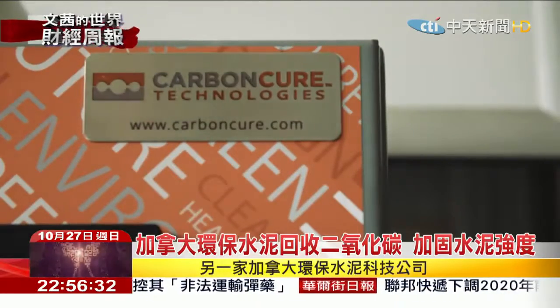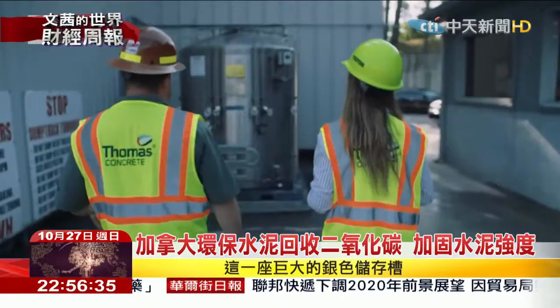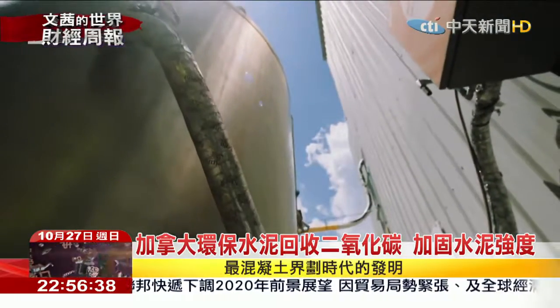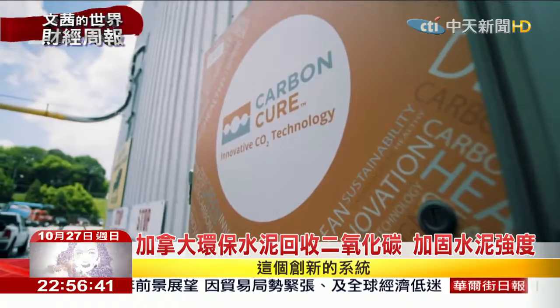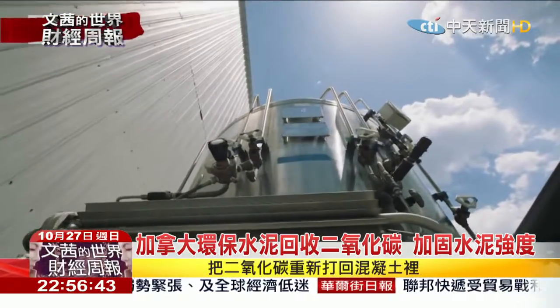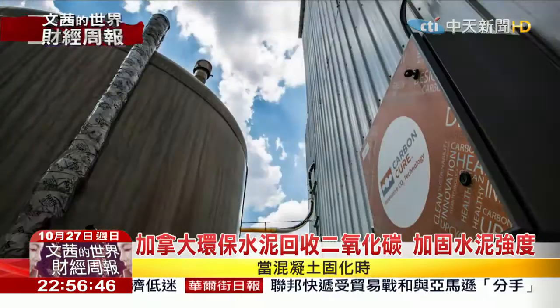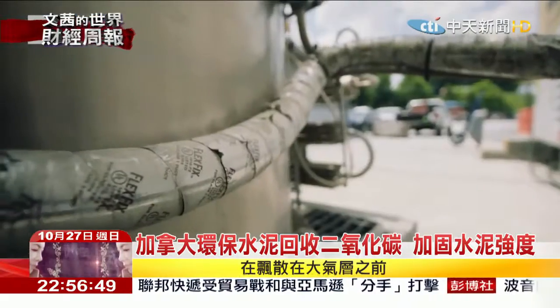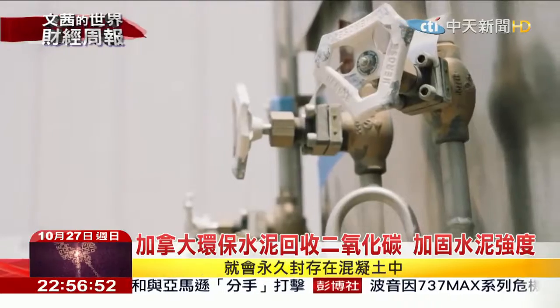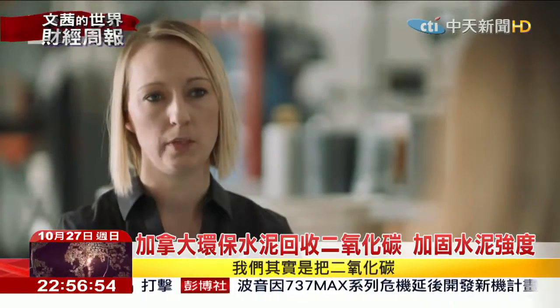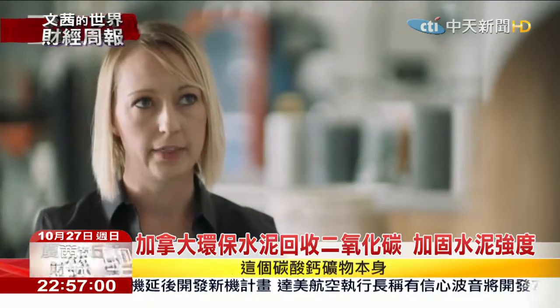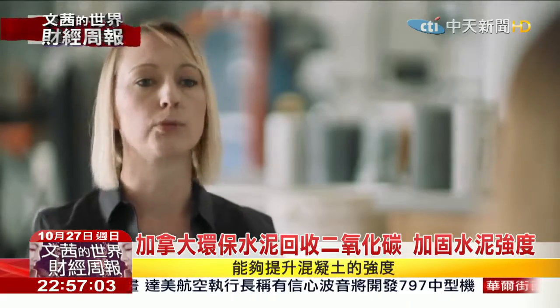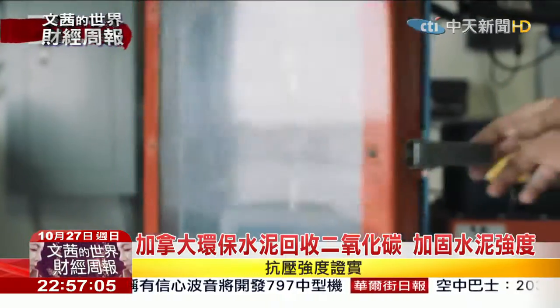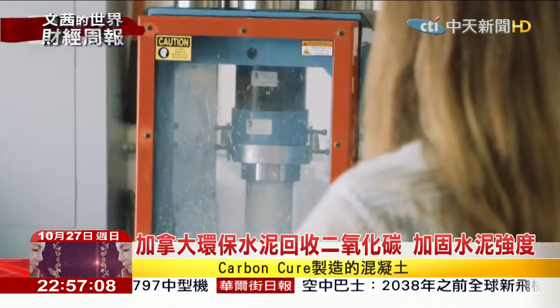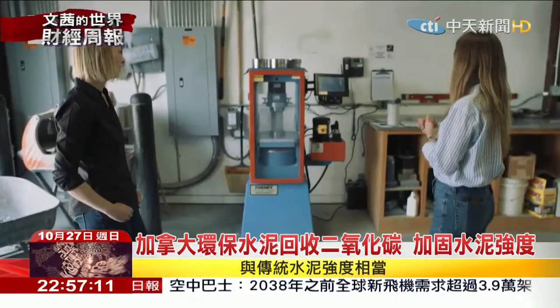This silver tank is the newest thing in concrete. It's called Carbon Cure. This innovative system injects carbon dioxide into the concrete as it's being mixed. When the concrete hardens, those otherwise harmful emissions are sequestered forever, before they ever even reach our atmosphere. We actually convert the CO2 into a mineral. It's a stone. It's getting trapped in the concrete forever. And the best part about it is that the mineral itself actually improves the compressive strength of the concrete. Compression tests like this one prove that the concrete made with Carbon Cure is just as hardy as the traditional stuff.